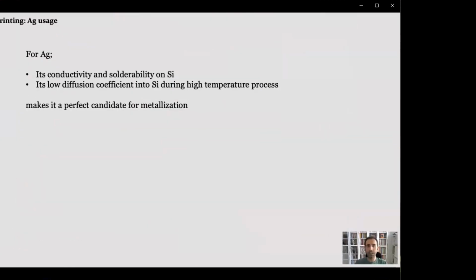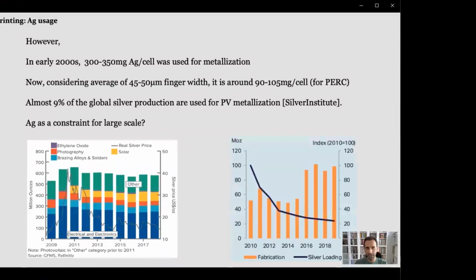Screen printed silver contacts has been the most utilized metal because of silver's excellent conductivity and solderability onto silicon. Its relatively low diffusion coefficient into silicon guarantees good contact with the substrate. Despite its great electrical advantages, its cost corresponds to almost 40% of the total cost.